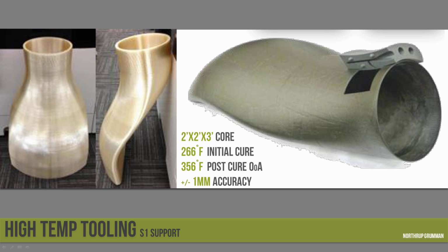Here's an example from Northrop Grumman. This is a high temp tooling using the S1 support. I like this example because it's very physically large. I put the size there. It's 2 feet by 2 feet by 3 feet core size. Notice that the tool is hollow over on the left there. It's basically just a shell part. And that's going to be important when it comes to actually breaking out the mold. Minimizing the amount of support material that you have to remove makes sense, whether or not it's soluble or breakaway, like it is in this case.